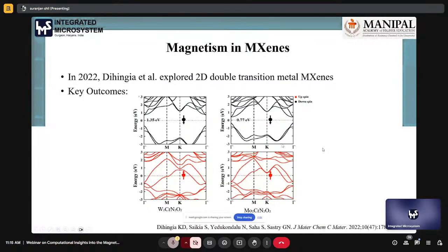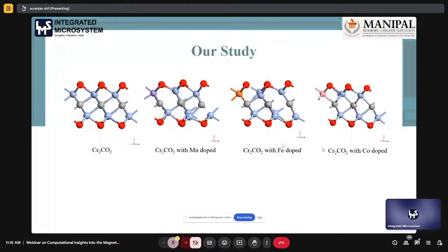So you can see that these materials have very promising electronic properties like half metallic behavior, conductor, semiconductor. We can tune all these properties based on the surface termination and the metals and the non-metals present in the materials. So now we have seen that we can tune the magnetic properties. We are interested in whether, if we dope these materials, the magnetic property will change. For that reason, we chose chromium carbide with oxygen termination, and we doped it with 3 different transition metals, manganese, iron, and cobalt, and we try to understand the change in their magnetic behavior or magnetic properties.